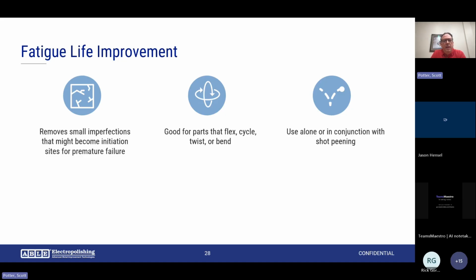Fatigue life improvement. Obviously, you'd be interested in this topic with springs. Electropolishing removes small imperfections that might become initiation sites for premature failure. It's good for parts that flex, cycle, twist, or bend. We do a flight-critical part for the Apache helicopter. It's a support for the main rotor, and it has to twist and flex under G forces. They use electropolishing to make sure there are no defects in the surface that are going to cause premature failure.